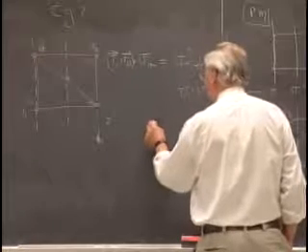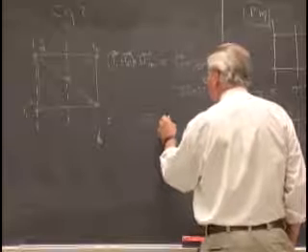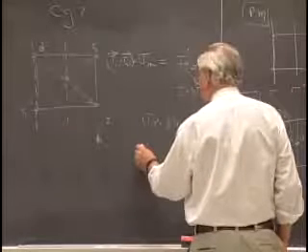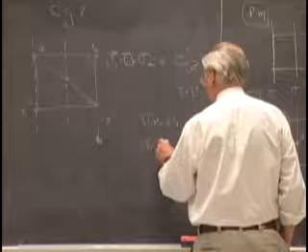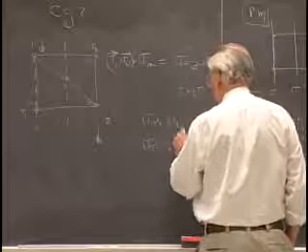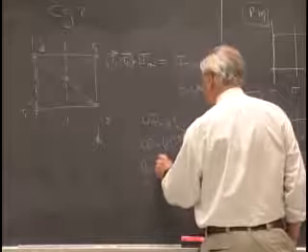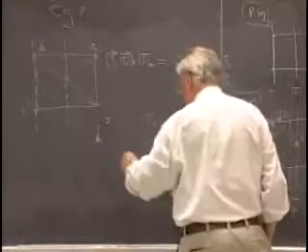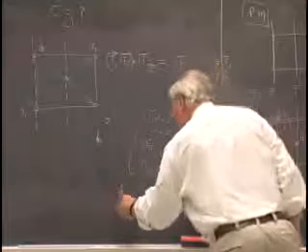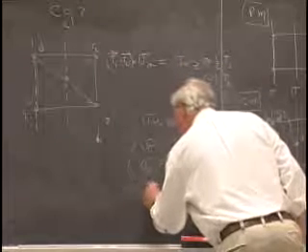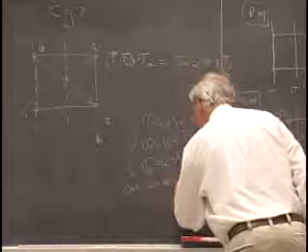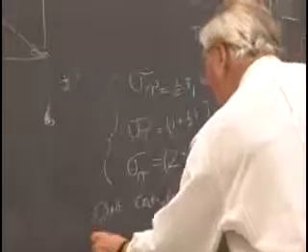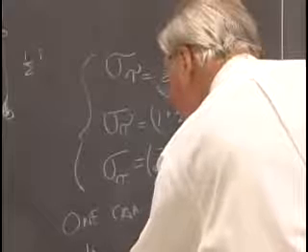Because if we have a glide operation with tau equal to one half of T1, and if this sits in a lattice, then there's going to be a glide plane that has tau equal to 1 plus 1/2 of T1. And it'll have to be another glide operation that consists of 2 plus 1/2 of T1. And the reason is that everything is periodic at an interval T1. So the moral that I'm trying to draw here is that one can add or subtract. To identify the actual nature of a symmetry element, one can add or subtract an integral number of translations.